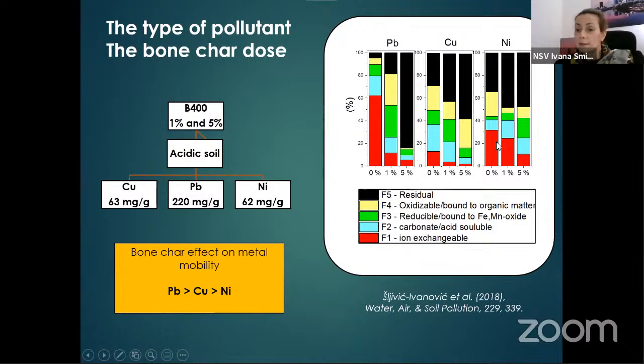It could be seen that in all cases, this red bar, which represents the ion exchangeable fraction of metals, which is most mobile and toxic, has decreased after the implementation of the bone char. Also, this decrease was connected with the bone char dose for every cation. However, the efficiency was not the same for all cations.